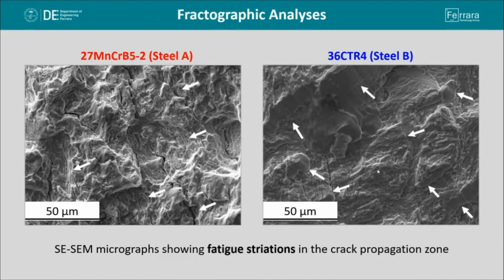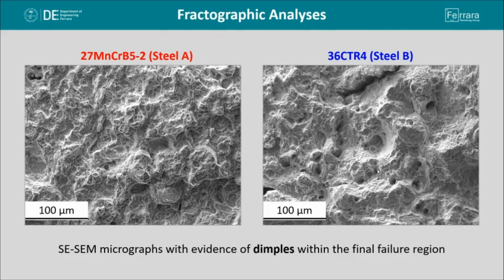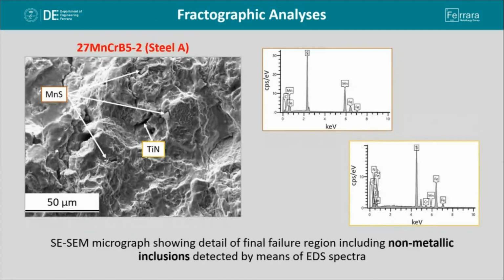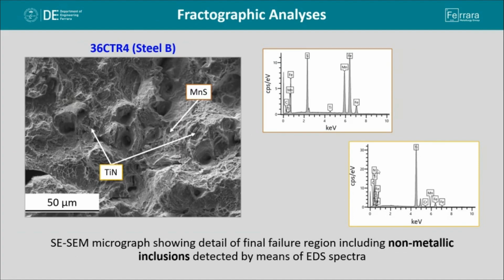Apart from fatigue striations detected within the crack propagation region, we also highlighted the presence of dimpled features within the final failure region. The presence of such morphologies could be justified by the evidence of specific non-metallic inclusions, such as manganese sulfides and titanium nitrides, which were in agreement with the chemical composition of the investigated steels. In fact, such non-metallic inclusions were detected not only for steel B, but also for steel A, as we can see in the EDS spectra included in the present slide. So we can assess that although we are dealing with different tempering temperatures and so different heat treatments, both the investigated quenched and tempered steels exhibited the same morphologies in terms of rotating bending fatigue behavior.